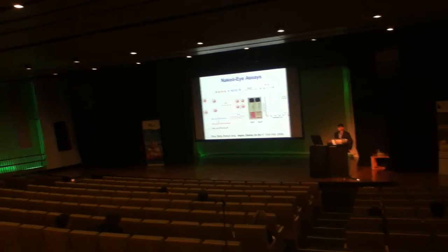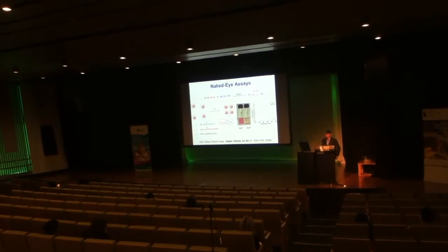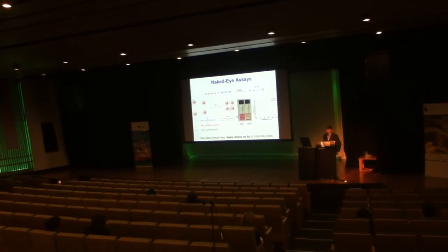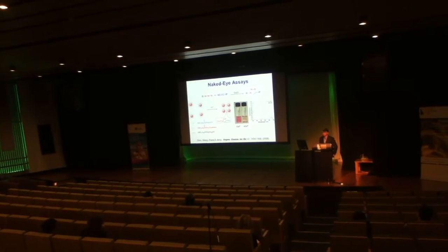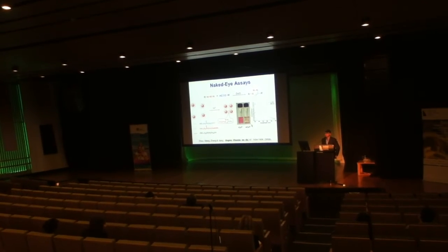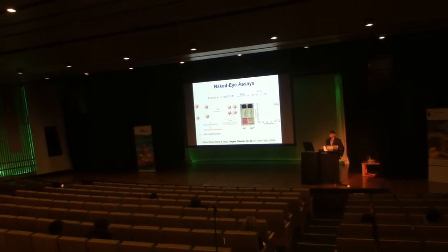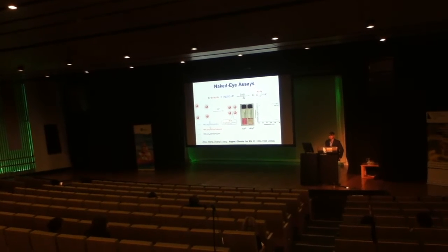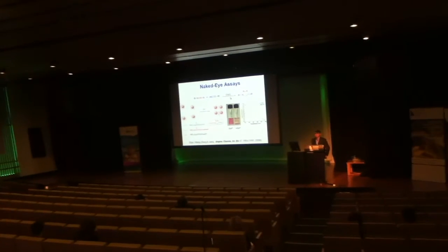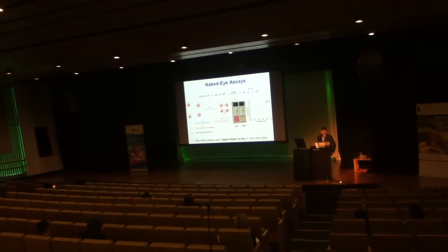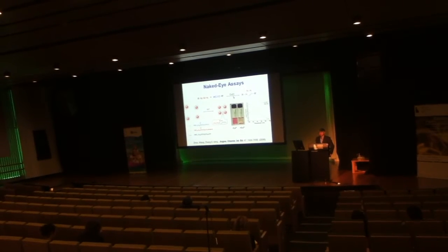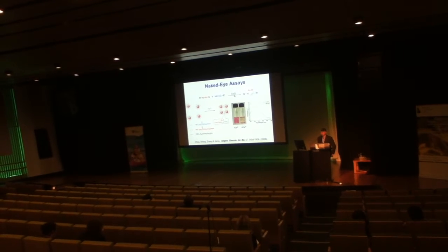Dispersed gold nanoparticles are typically this pinkish color. Aggregate gold nanoparticles in aqueous solution is typically bluish purple, or if it's completely aggregated, you get a clear solution with precipitate on the bottom. So our thought is to use this to detect copper because it's very selective. Only copper is known to catalyze this reaction, and also because copper is used as a catalyst, a very small amount of it could catalyze this reaction, so that may potentially lead to high sensitivity detection.